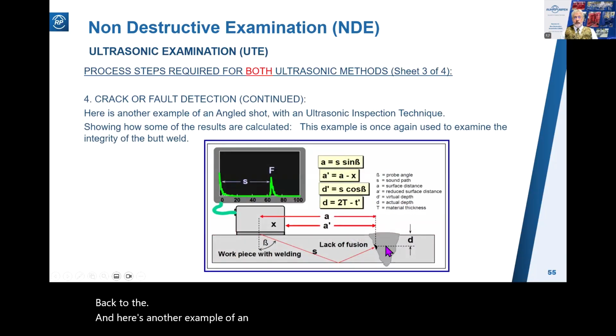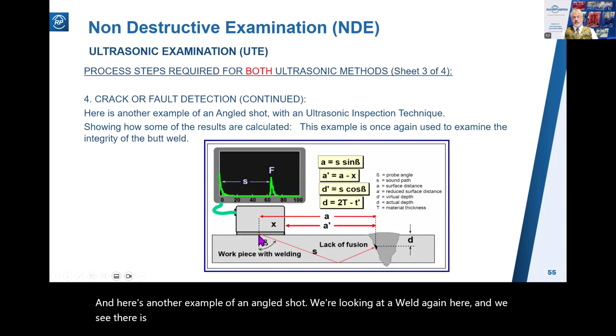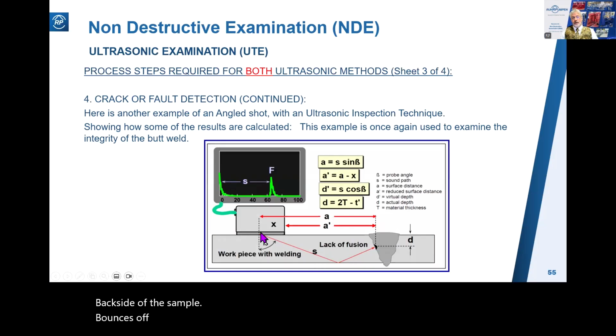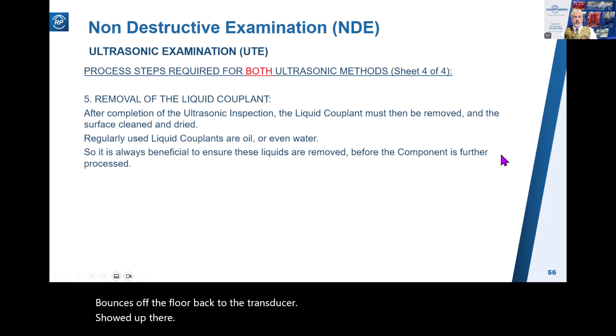And here's another example of an angled shot. We're looking at a weld again here, and we see there is a lack of fusion there, which is detected by the beam bouncing off the backside of the sample, bounces off the flaw back to the transducer. Showed up there. Next stage, as usual, it's cleanup.